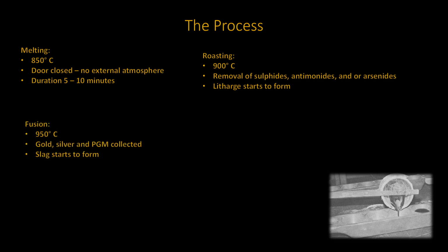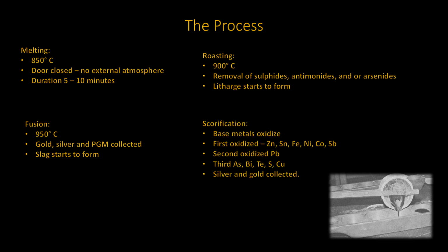When the roasting stage is decided as being completed, the temperature is further increased to 950 degrees centigrade and maintained. During this fusion stage, any remaining undecomposed material will start to fuse and disappear. Any silver, gold, and, if present, any PGM group metals will be collected in the remaining elemental lead. The slag will start to form a wide ring around the molten lead button in the center of the dish. It is at this point the scorification process begins.